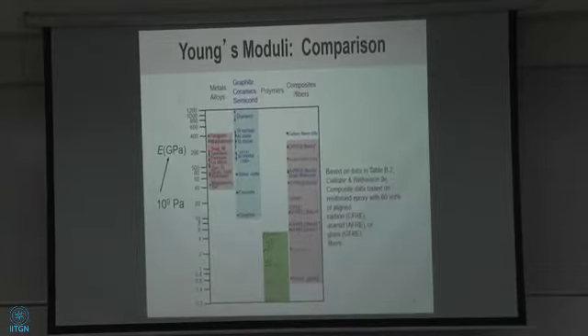Steel and nickel are right about there, about 240 GPa. And here you have about 40 to 43 GPa. And then here you have diamond. Diamond is right there, pretty high. High elastic modulus. Graphite is right there. This is the pencil that you use, right? Graphite is right there, soft. There are your carbon fibers.